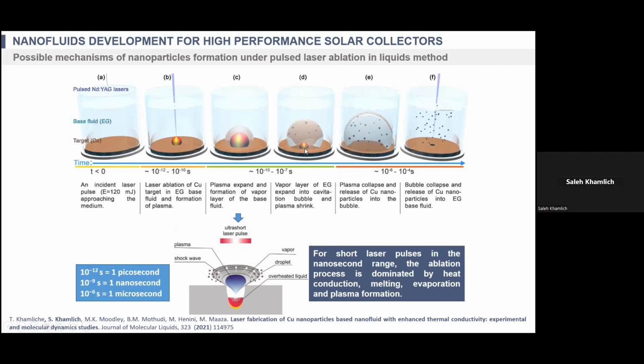And while this plasma is shrinking, because it contains the atoms of the copper, these atoms attract each other to create nuclei, and these nuclei will create nanoparticles inside the cavitation bubble. Once the cavitation bubble collapses, the nanoparticles created inside will be dispersed inside the liquid. Very simple process, but it's an elegant process. And it's a very clean process.